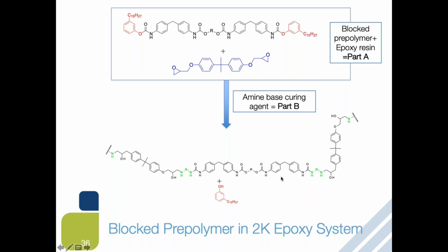What will happen is that, as you know, typically amine and epoxy reactions are quite fast with a relatively high exotherm. That exotherm will be helpful to initiate the deblocking of the cardanol. And at the same time, having the amine, which we talked about earlier as a very effective deblocking agent, lowers the deblocking temperature. So in this whole system, you have exotherm and amine, and they will assure that the deblocking of the cardanol will happen.